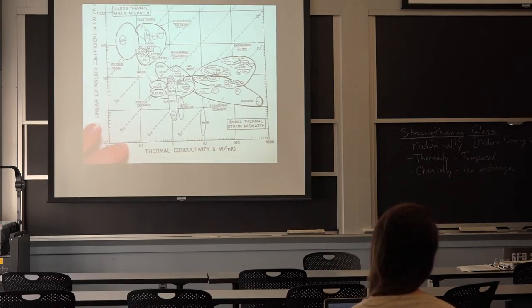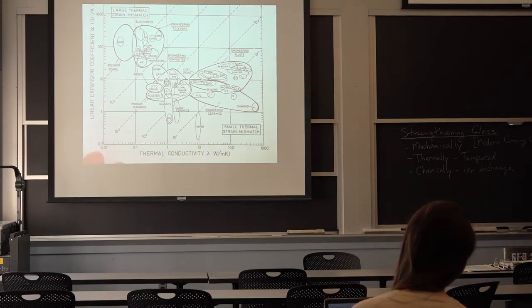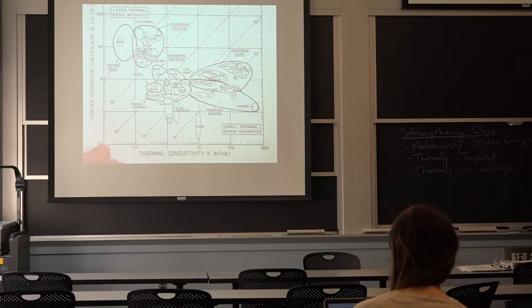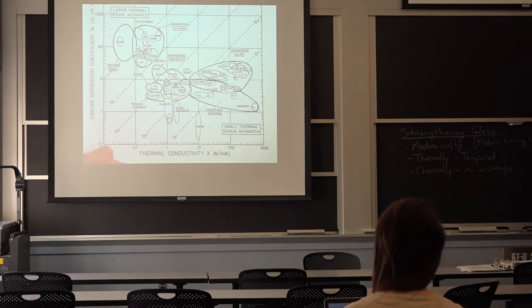Turns out glass is still a brittle material. It has lousy thermal conductivity compared to diamond, which has got the best thermal conductivity. So we're looking at thermal conductivity versus linear coefficient of expansion. Diamond is out here by itself with fantastic thermal conductivity, very strong bonds, which is one of the things. The metals are up in here. Some of the ceramics are back here underneath the metals. The glasses are way down here, so far as that goes. This is some of the engineering ceramics. And your woods and things, your plastics are in here. But in any case, the glasses are in here.